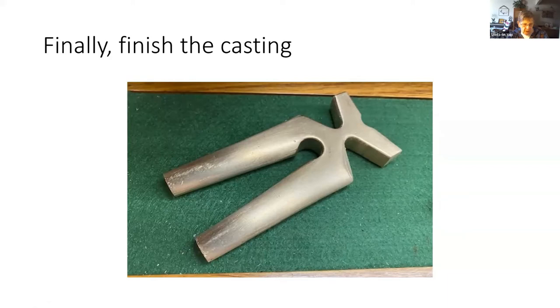The gate area is all taken off — it was not part of the original design, so that would have been sawn off. Those air vents and wires would have been nipped off. The surface of the casting is smoothed with a combination of sandpaper and grinders; a saw separates the sprue from the casting body. Sometimes we'll have to do some filling as well, typically with a similar type of bronze wire, heating it up with a torch.